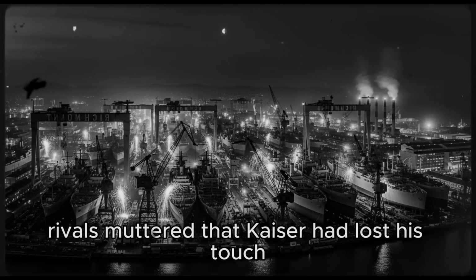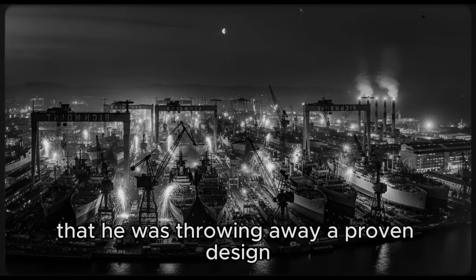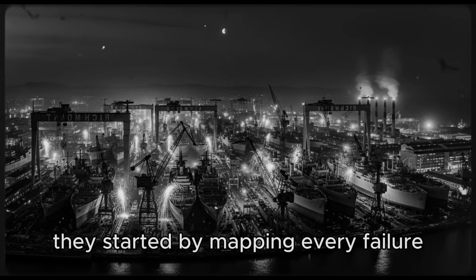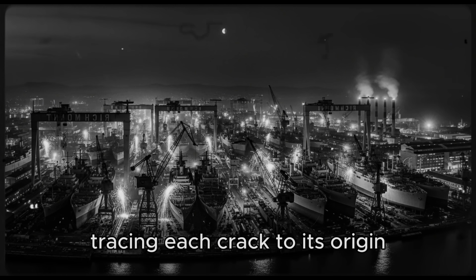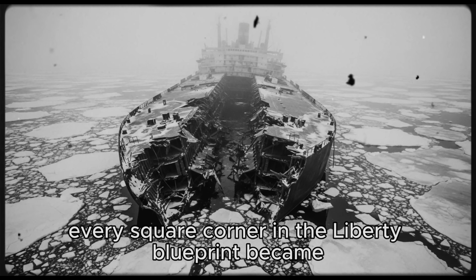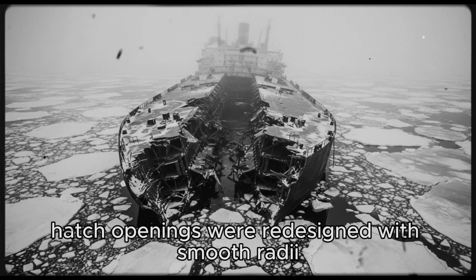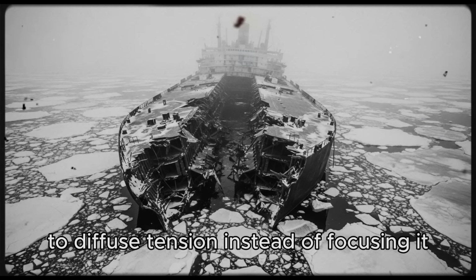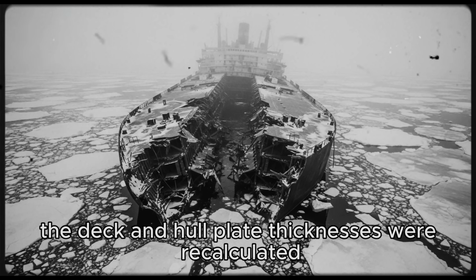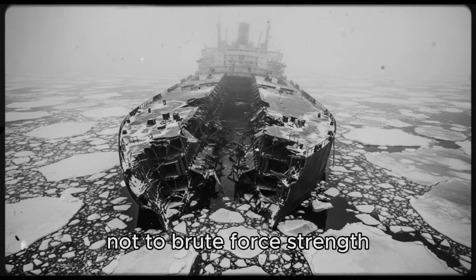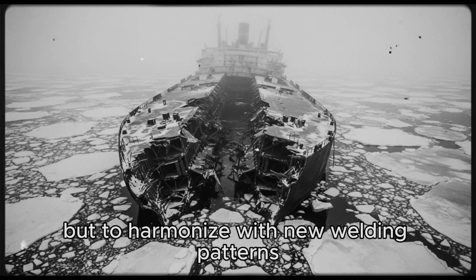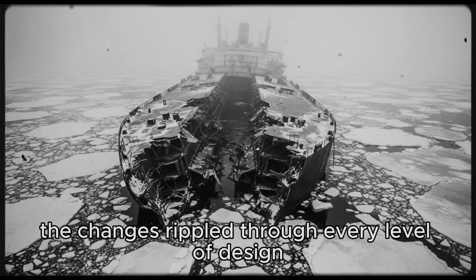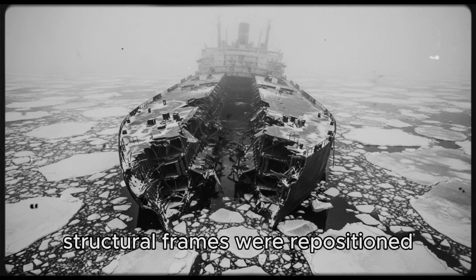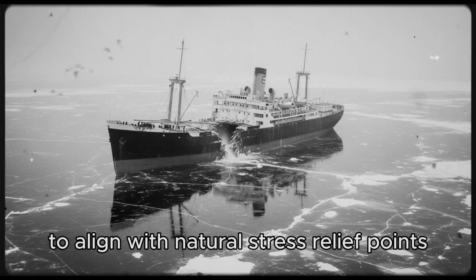Congress prepared investigations. Rivals muttered that Kaiser had lost his touch, that he was throwing away a proven design in a moment of fear. But the engineers pressed on. They started by mapping every failure, tracing each crack to its origin. Every square corner in the Liberty blueprint became a curve. Hatch openings were redesigned with smooth radii to diffuse tension instead of focusing it. The deck and hull plate thicknesses were recalculated, not to brute force strength, but to harmonize with new welding patterns. The changes rippled through every level of design. Structural frames were repositioned to align with natural stress relief points.